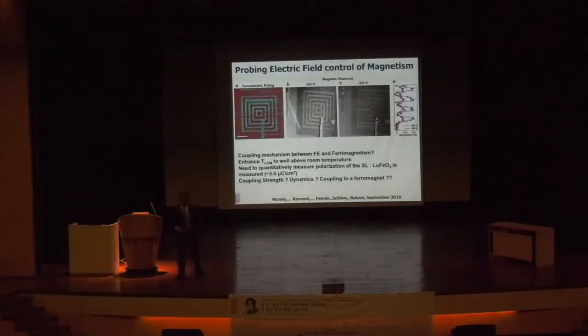But you can take that pattern now and ask the question, hey, tell me what happens to the magnetic degree of freedom. Right? I have switched the ferroelectric, the charge degree of freedom, from up to down. I can go back to the photoemission microscope and do circular dichroism measurement of the magnetic degree of freedom. That's what this data is. What it's telling you is that, indeed, the magnetic degree of freedom at 200 Kelvin, albeit, is switching in response to the polarization degree of freedom going up and down. And it goes away by the time you hit about 300, 320, because the Curie temperature of the ferrimagnet is about room temperature, 300 Kelvin. So it tells you that indeed this notion is doable.